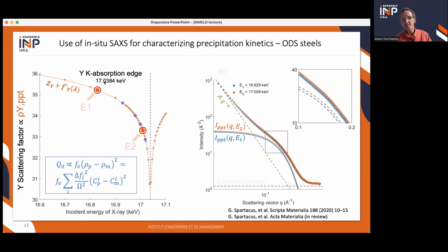If you have this element within the precipitates, then by changing the energy, you will see the intensity changing. If, on the other hand, you don't have this element in the precipitates, then the intensity will be the same at the two energies. So really, this anomalous effect helps you to probe the presence of one element within the particles. And when you do that, you can see the difference is quite subtle. You need to make very careful measurements because at two energies, you see a slight change of intensity that you can try to understand.